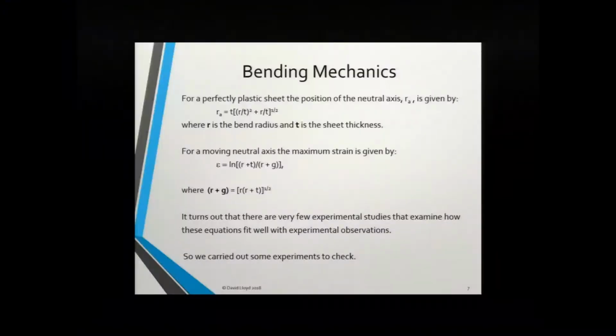And for a perfectly plastic sheet, which is what the mechanics models basically assume, the neutral axis radius is given by this top equation. So it's a function of, as you'd expect, the radius of the bend and the thickness of the sheet. For a moving neutral axis, the maximum strain is given by this equation. It's a tad more complicated, but essentially the parameters are the same.